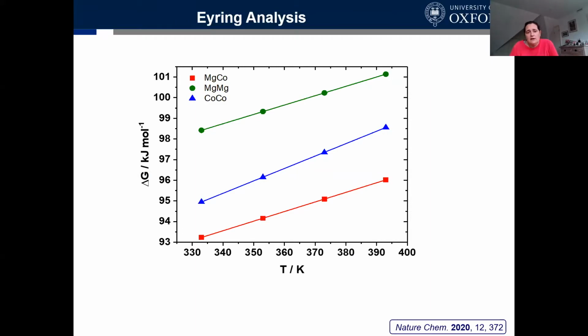So the next thing we did was to do an Eyring analysis. Here you're looking at the temperature dependence of the rate constant, and you're using that to extract the transition state Gibbs free energy. And we can see that for our series of catalysts, there are differences between them. They're quite small, but the error bars in these numbers are very low. And so they are real, and exactly as you'd expect, a magnesium-cobalt compound has the lowest transition state energy, whereas the magnesium compound, which is the slowest catalyst, has the highest one over a range of different temperatures.